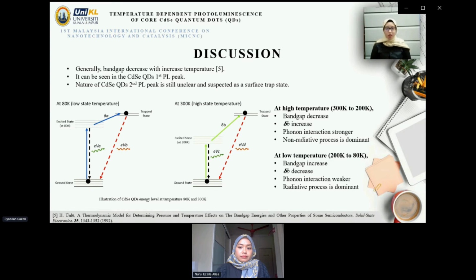At high temperature, the non-radiative process is dominant, and more phonons are released. It is suspected that both emission processes come from non-radiative recombination that leads to emission from the trap state to the ground state of quantum dots. At high temperature, most emission of quantum dots is coming from non-radiative processes, involving phonon interaction. As temperature reduces, the phonon interaction will become weak, and the radiative process will dominate the PL process within quantum dots.